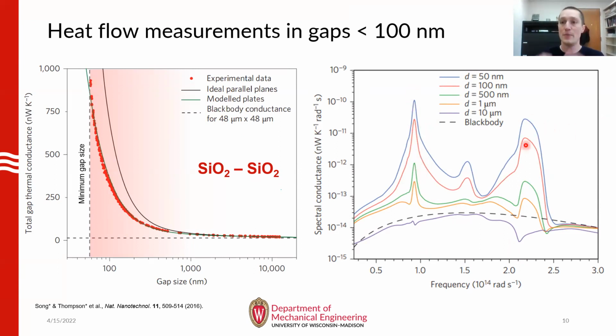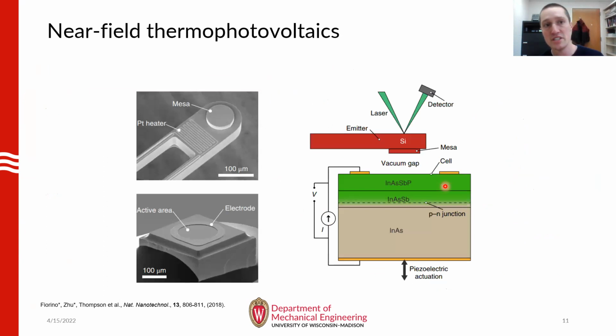And it turns out that it's in these spectral regions where surface phonon polariton modes are supported at the surfaces of these silicon dioxide surfaces. Okay, so because of that, it turns out that it's the coupling of these resonant surface modes that's responsible for the large enhancements in conductance that we observe. Okay. Now, we actually leverage these near-field effects in a follow-up experiment demonstrating thermophotovoltaic energy conversion.